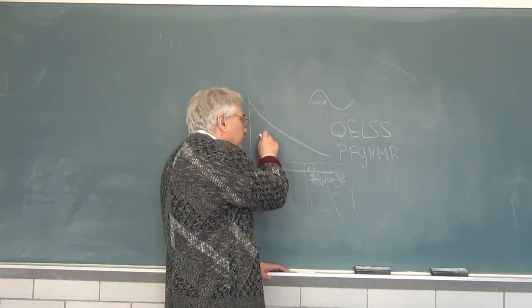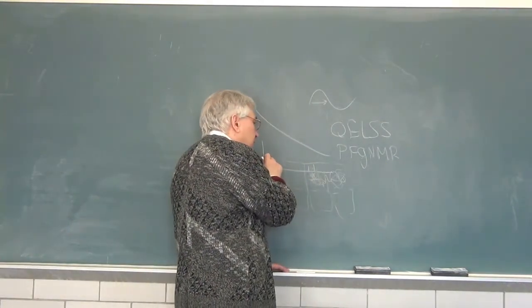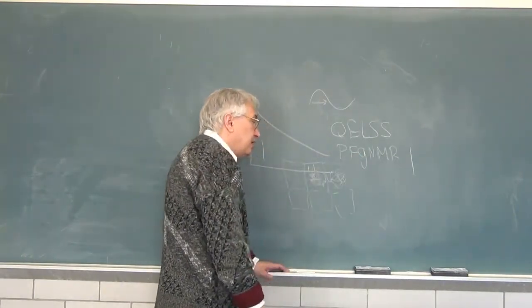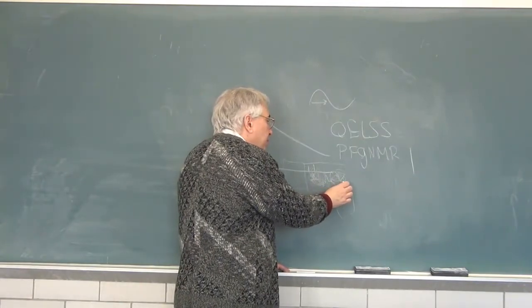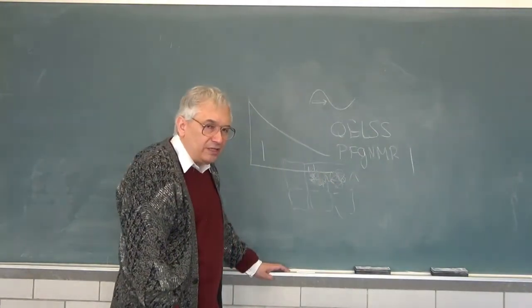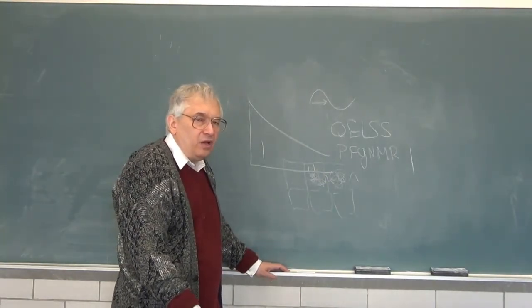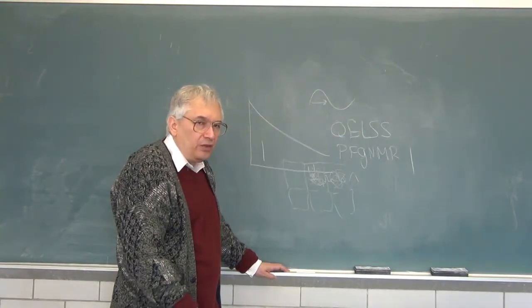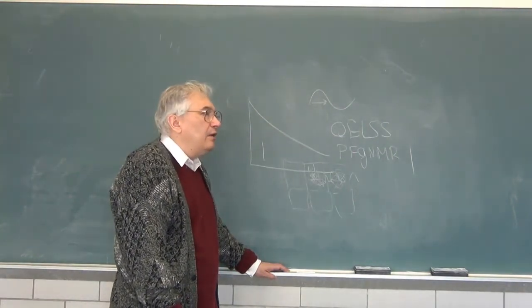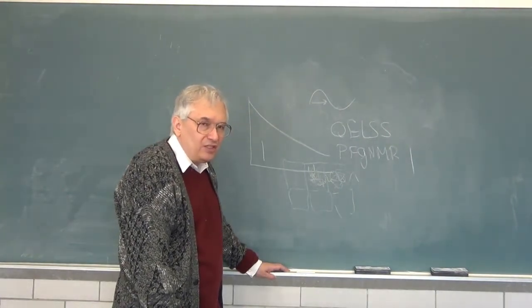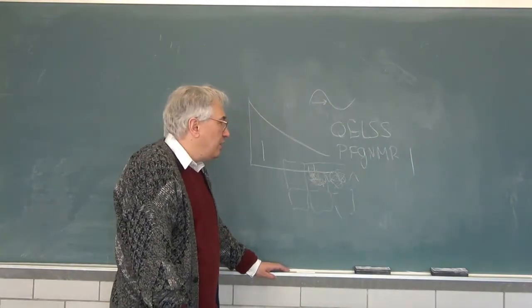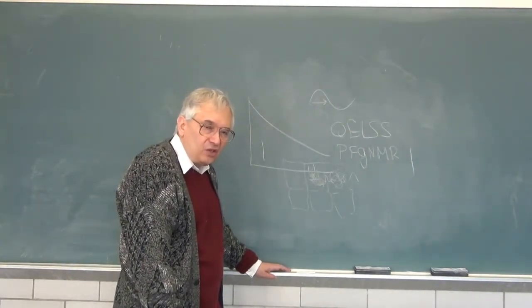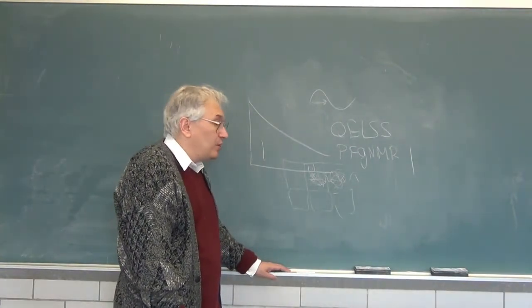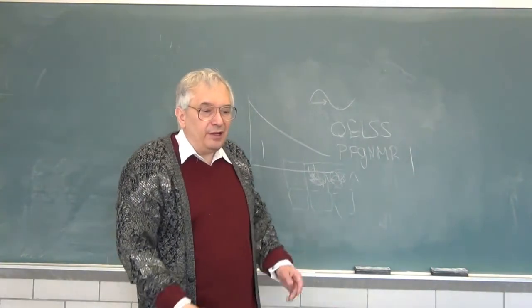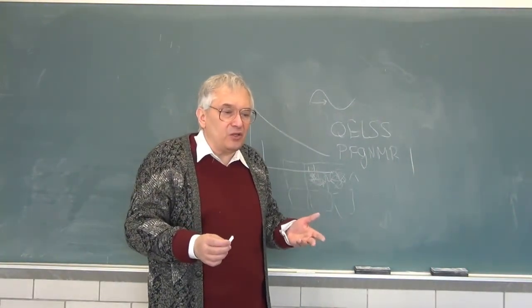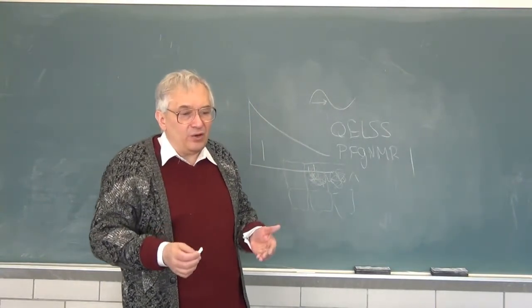If, however, you do use a measurement of diffusion which asks how long does it take the particle to get from here to here, that's pulsed field gradient NMR, the particle has to hop repeatedly from box to box, a slow process, and in this case, the diffusion found on long distance scales is slower than the diffusion found on short distance scales. I urge you to reread the papers of Nemoto where precisely the opposite circumstance is found. The long distance diffusion seems to be faster than the short distance diffusion. I don't have a pretty picture that shows you how you get that second result. Nonetheless, the core issue is Davis did measurements on several different distance scales and he found the same results.